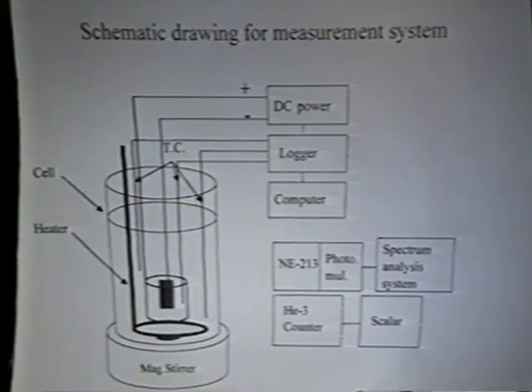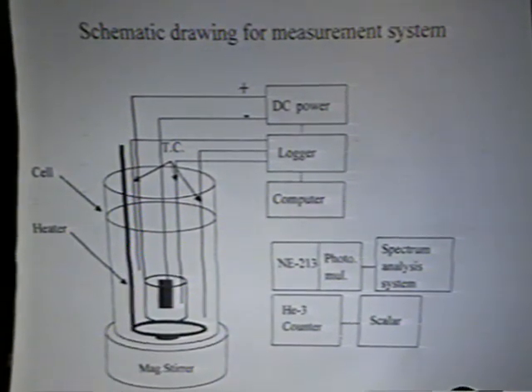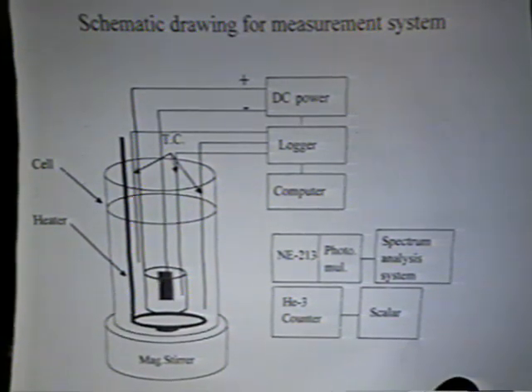This is a schematic drawing of my experiment system. Basically, the electrolysis cell is a very conventional type. It is made of quartz, 5 centimeter diameter and 15 centimeter height. Temperature was measured by Teflon coated thermocouple at 3 points. Heater was used for calibration. All the data, temperature, input voltage, and current were accumulated on floppy diskette through a data logger. Here, I have designed to measure neutron count and energy spectrum by helium-3 and NE213 scintillators.